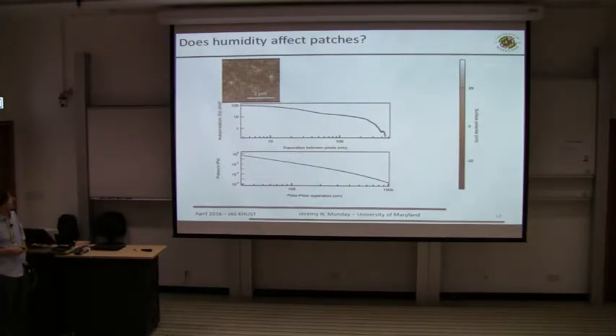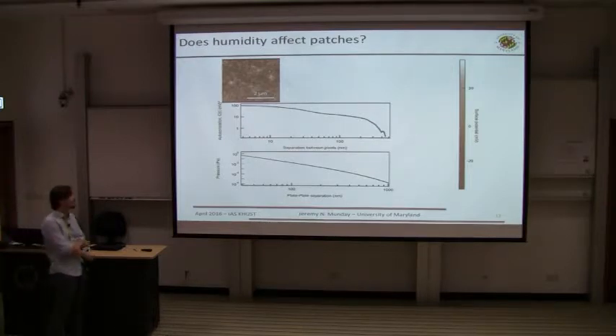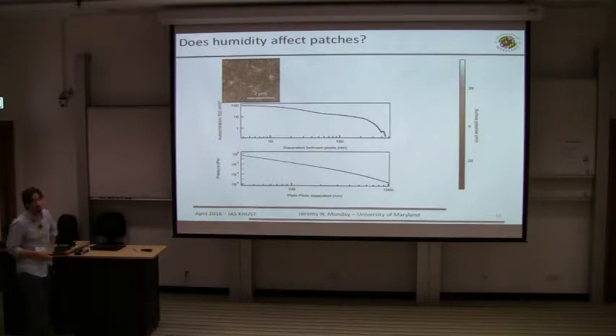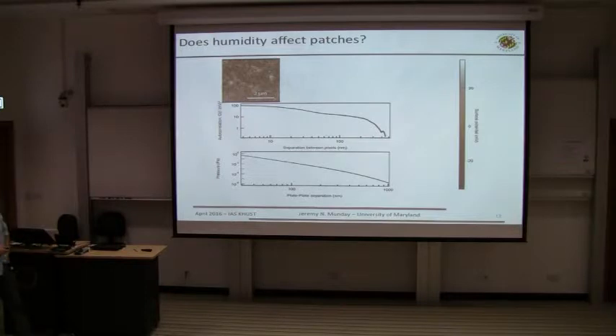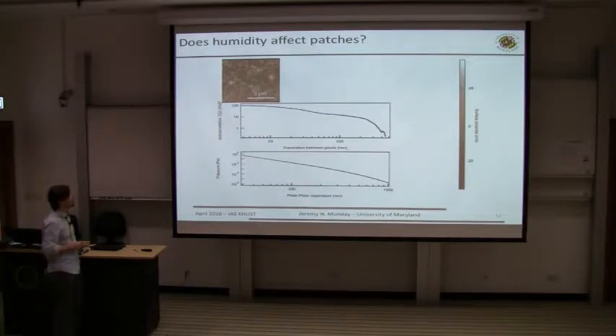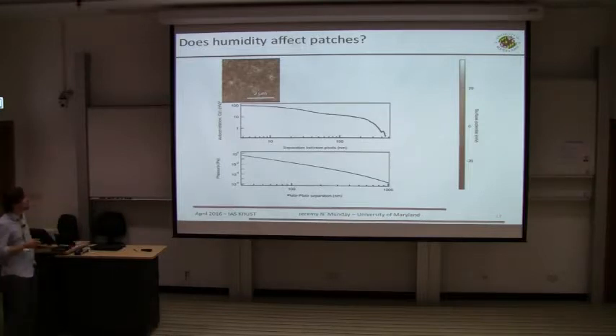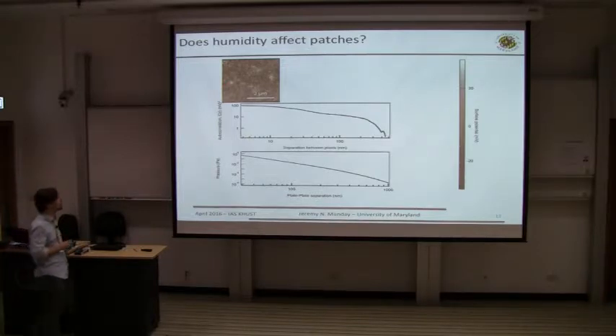So the other thing is, how does humidity affect patches? So the experiments we're doing are in ambient conditions. And so we wanted to see over the course of a day, or if we purposely change the humidity, how that affects it. And so these are the patches here under, I believe it's about 20 to 25% humid environment, and we're going to start letting it get more dry. But here's the autocorrelation function, so the autocorrelation between the different values of the voltage spatially distributed as a function of the separation that we have between the pixels here.